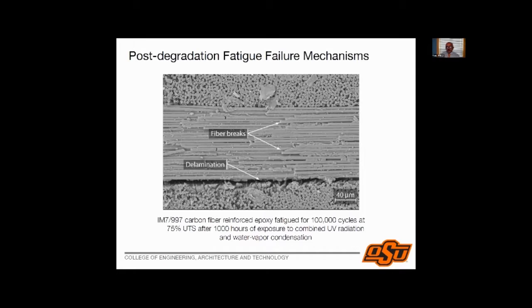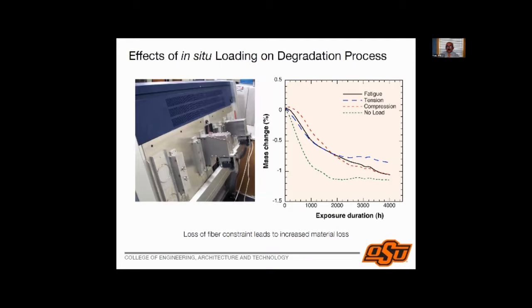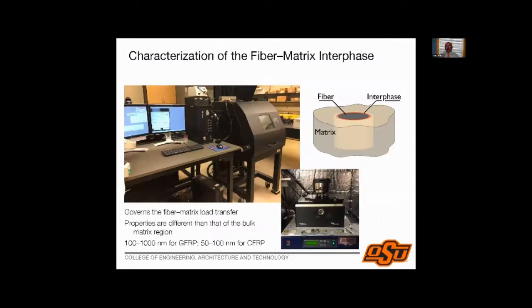This breakdown affects everything. This primarily affects things like fatigue. So if I take the composite laminate that has been subjected to degradation and I subject it to fatigue, the fatigue life is much less than what it would be otherwise. We did quite a few experiments, primarily in terms of understanding fatigue, and also in trying to understand if I had loading, how that would end up affecting the degradation process. And we found that depending on how I was loading the composites was also affecting the degradation process, right? So this is the background which basically gets us to today.